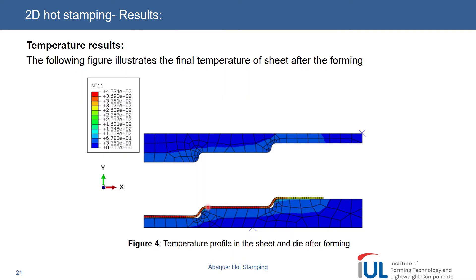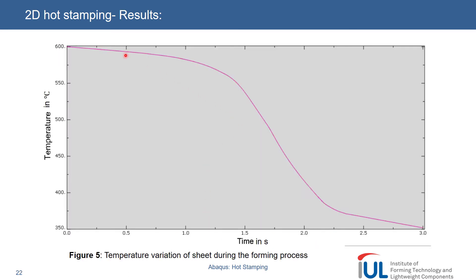I've checked this curve at the point where there is curvature and where I can expect heat flux to be more - where heat transfer is higher. Up to about two seconds, this is the area where I think contact has started, so there is very little heat lost due to radiation and gap conductance. When contact starts, you can see the temperature decreased to below 400 degrees within two seconds. Within 2.1 seconds I set this up so we get to this curve, which depends on the CCT curve - the continuous cooling transformation curve - so the microstructure becomes martensitic.